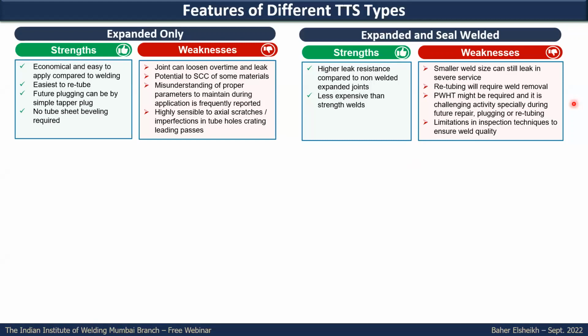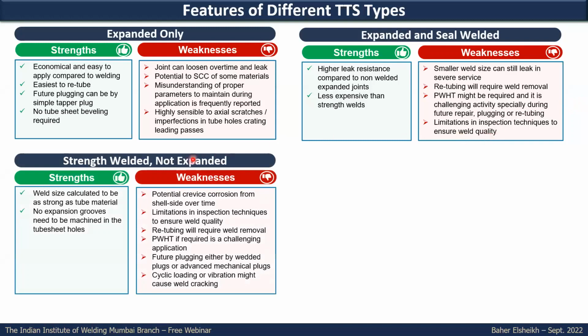And in case post-weld heat treatment is required, especially for service reasons, it will be of some interest during the initial construction. The main concern here will be during plugging or retubing. To do post-weld heat treatment at site is not an easy application, to have uniform application of the post-weld heat treatment. And there is also the limitation of the inspection technique for the weld, and this will be a common limitation for all the weld joints.